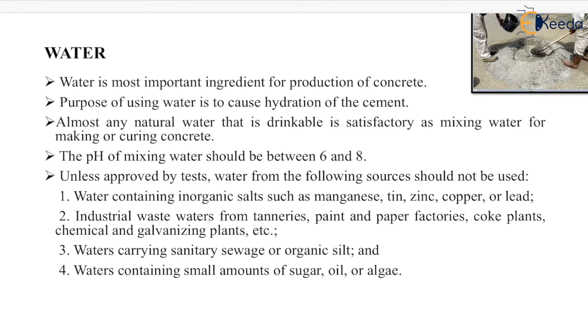Unless approved by test, water from the following sources should not be used: water containing inorganic salts such as manganese, zinc, copper, or lead; industrial waste water from tanneries, paint and paper factories, coke plants, chemical and galvanizing plants; water carrying sanitary sewage or organic silt; and water containing small amounts of sugar, oil, or algae.